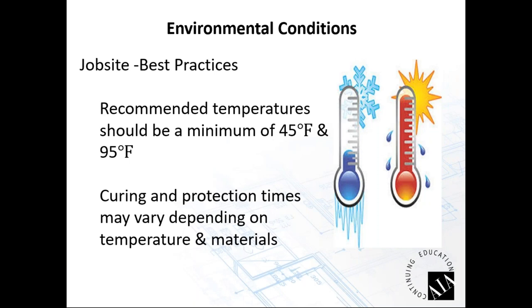So when we look at job site practices and the best practices, recommended temperature should be a minimum of 45 degrees Fahrenheit and 95 degrees. Now what this means is that not only the air temperature, but the ambient temperature of the surface conditions that you're working on. So let's say, for example, we're doing a project in Arizona and it's going to be in the summertime, and we know that the air temperature is going to be hitting up to 110 degrees. That means the surface temperature of the substrate that we're going on could be a lot higher, 150, 160, maybe all the way up to 180 degrees, depending upon how it's facing in the sun.